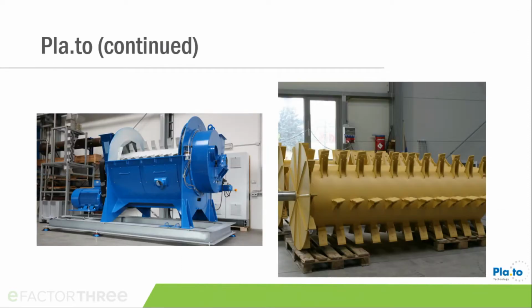And that happens inside that machine. This is the friction rotor inside that machine that creates a lot of force on the material, and we have a multi-edge screen basket around it. So it allows for a lot of friction, and it basically opens up the packages of stretch to single layers. It fluffs it up, so when it comes out, you're looking at 1.5 pounds a cubic foot at the most. You can stuff your pillow with it.